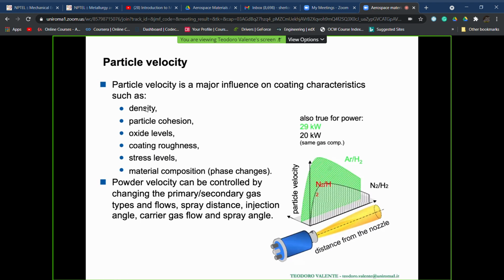Talking about the most important processing parameters which can influence the results in terms of coating quality in the class of technology which is said to be plasma spray technology. In addition to what we have already seen, we need to take into account also a very important item, particle velocity, as a processing parameter. Because the particle velocity, as we can understand, has a very high influence on coating properties such as density,